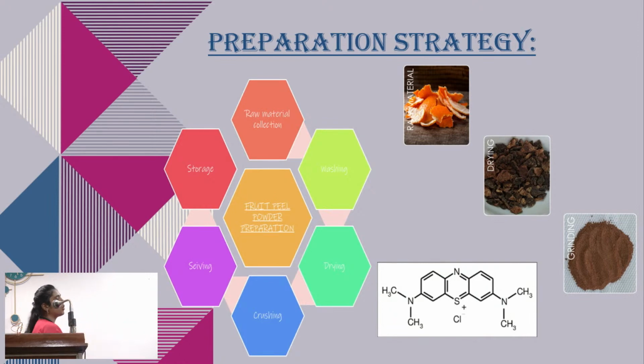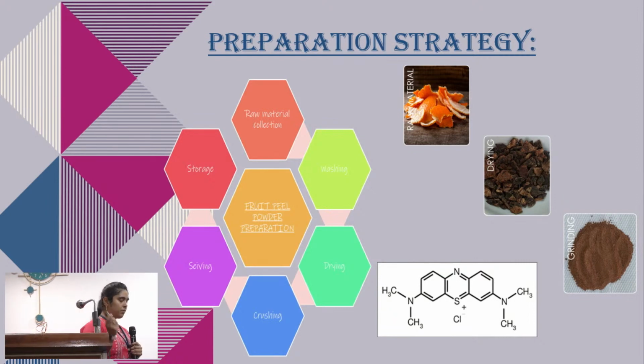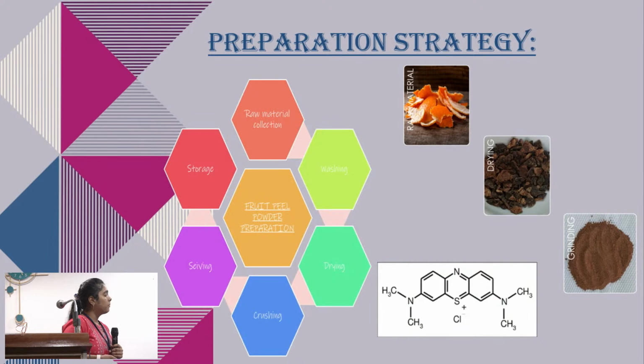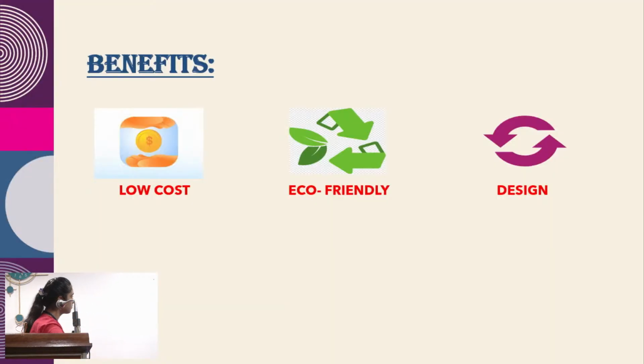This is the dye I took for my study, methylene blue. The attraction between my dye and the adsorbent is purely electrostatic. My adsorbent has negatively charged particles on its surface, and my dye has a positively charged group. This is known as the chromophoric group, which is responsible for the blue color of methylene blue. The negatively charged particles in the adsorbent attract the positively charged part of the dye, also known as the thiazine group. Therefore, the color gets removed. That is why I chose these adsorbents.